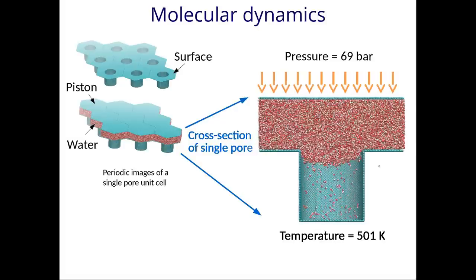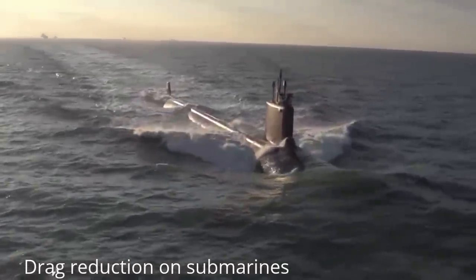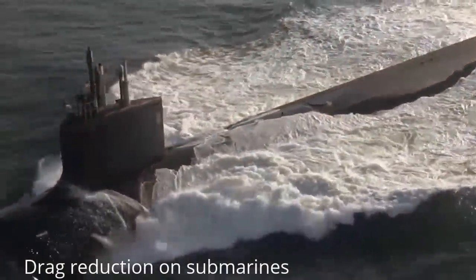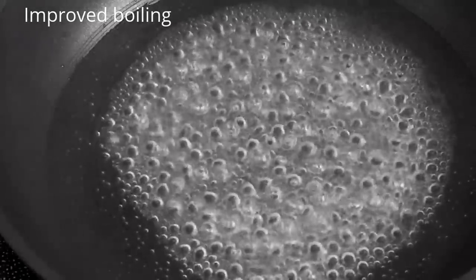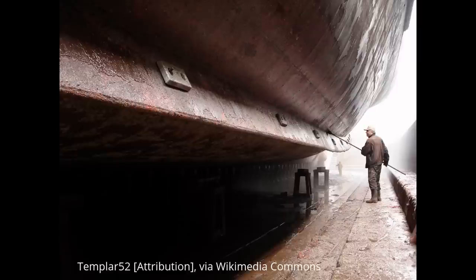Why is this significant? Gas within roughness grooves could help reduce drag on submarines. It is difficult to keep air within roughness grooves at large water depths, as it will dissolve into the ambient liquid. However, vapor can persist despite this. Superhydrophobic surfaces can also be used to help initiate nucleate boiling. There is also potential for anti-fouling capabilities on ships, as ships with minimal liquid contact reduce their interaction with marine life.